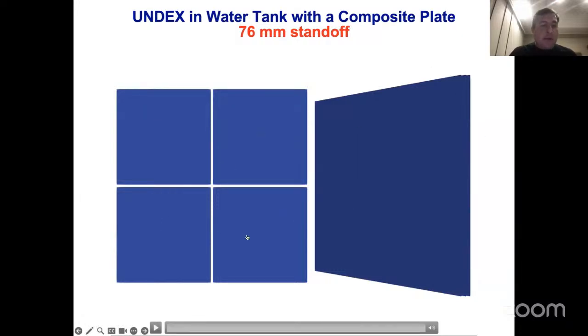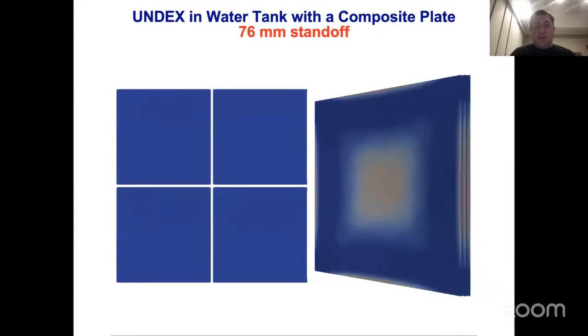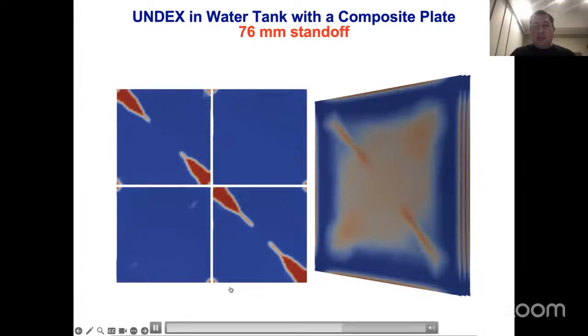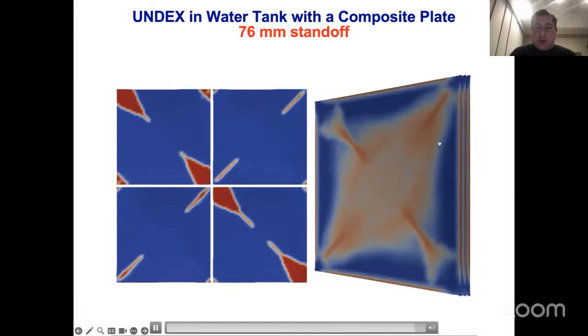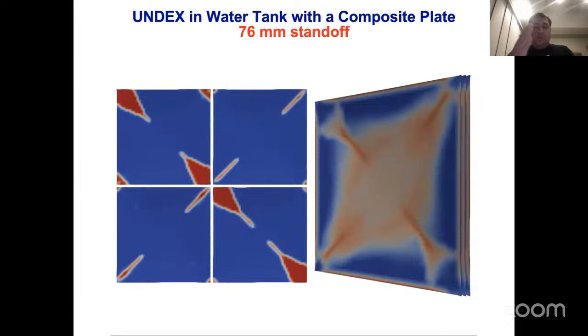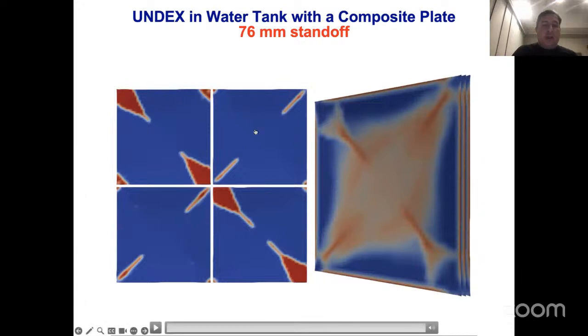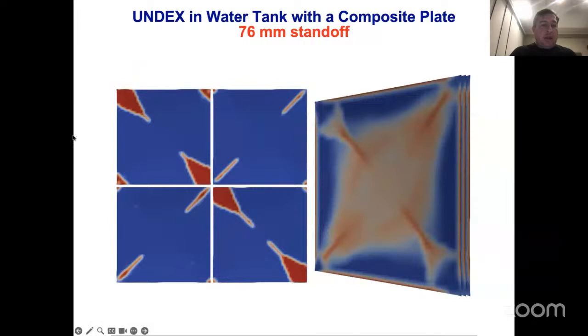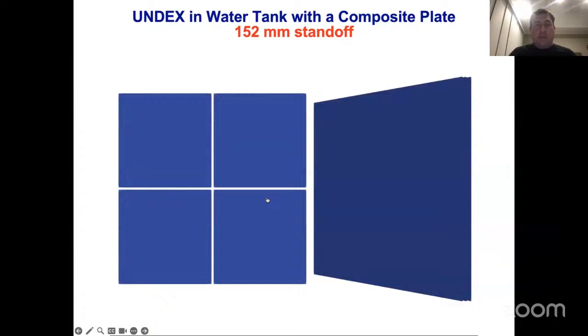And fiber damage with a 76 millimeter standoff. And what you see is that cohesive damage occurs first, okay? Then the different lamina start to basically act in an independent fashion. They can't support as much load, and you start seeing the formation of fiber fractures here, right? These are plus minus 45 plates, and you can actually see that pattern of plus minus 45 fiber fractures.